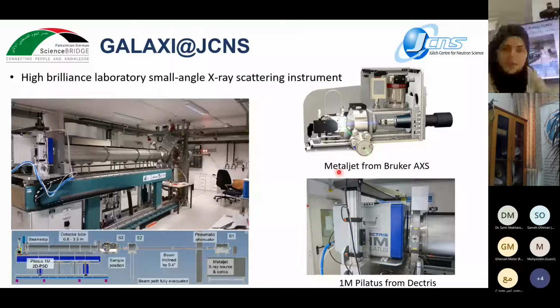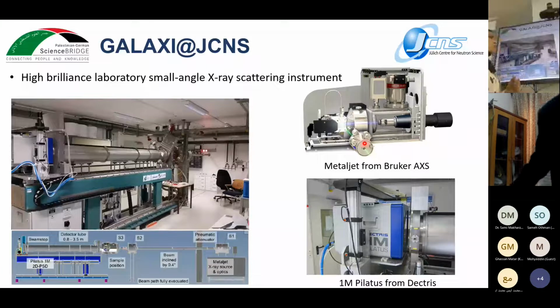So we have here the X-ray source. We have a liquid metal jet of a gallium-indium alloy. If an electron beam with an energy around 70 keV hits the liquid metal material, then the X-rays are produced.